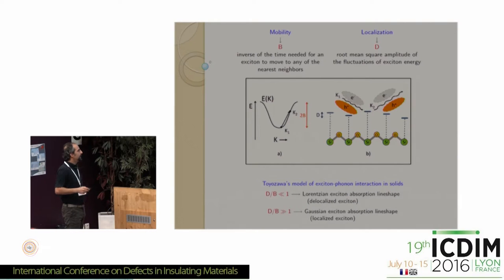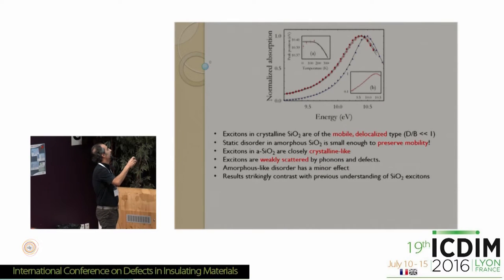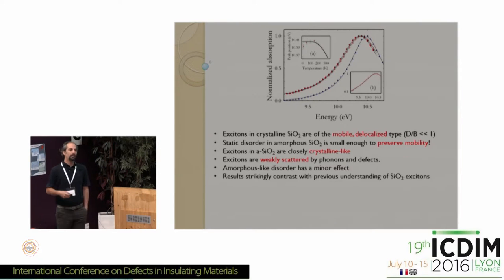So the interesting fact is that the theory predicts that excitons which are mobile are associated with Lorentzian absorption line shapes. Otherwise, if mobility is hindered by disorder, you have Gaussian line shapes. So the fact that we found very closely preserved Lorentzian line shapes means simply that the excitons in both crystalline SiO2 and amorphous SiO2 are very mobile. So disorder, both thermal disorder, but also structural disorder in the amorphous version of the material, is not strong enough to hinder the mobility of the exciton.